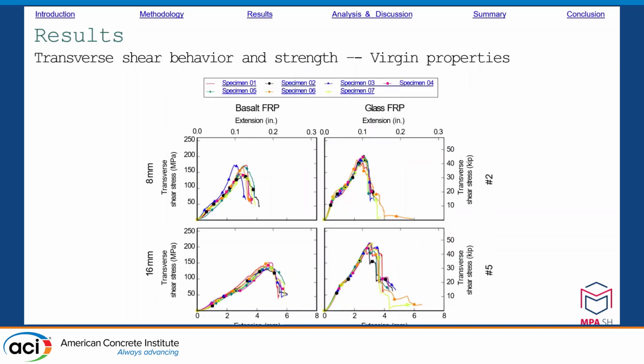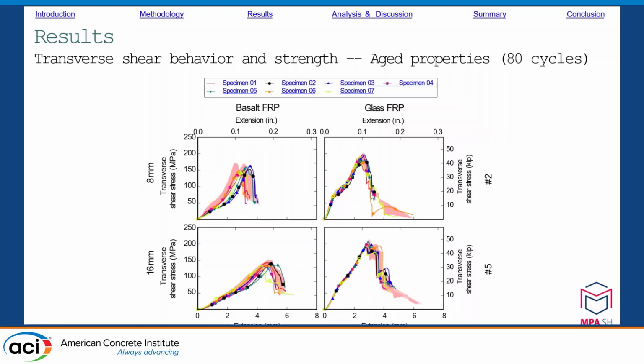The results of the transverse shear strength test also show an increase until the maximum shear force is reached and a subsequent drop in the curve. Here, the glass fiber rods achieve higher maximum stresses than the basalt fiber rods. The bars, which were preloaded with 80 freeze-thaw cycles, show only slight deviation from the previous curves. The maximum value reached approximately the same level as before.